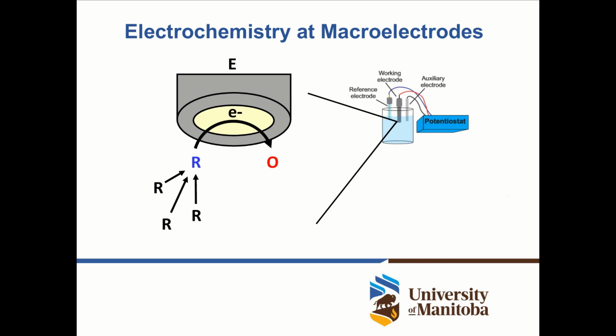In any case, electroanalytical chemistry involves an electrochemical cell, shown here on the right, where we have a vial that contains an electrolyte. When we measure cells, this is an aqueous solution, and we have 3 electrodes. Our working electrode is where the chemistry happens. This is mainly a metal wire, sealed in a glass capillary or any insulating material. It could be epoxy as well. Then we have an auxiliary electrode that closes the circuit, and a reference electrode that gives us a steady reference point so that other people across the world can understand the voltages and potentials that we are measuring.